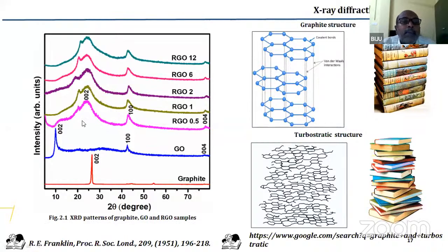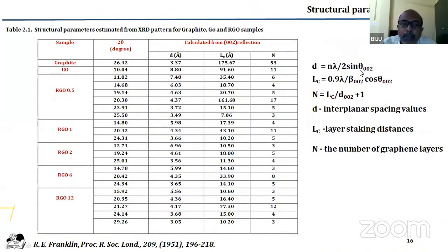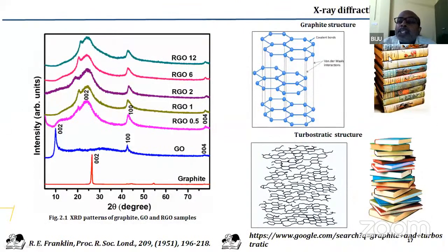Actually this broadening has happened due to the fact that when these layers are restacked, they are stacked in a disordered manner. In fact, this blue diagram shows a typical graphite structure, whereas the bottom one shows what we have obtained, which is called a turbostratic structure. As an analogy, we have shown graphite layers like books which are properly arranged, where the layers are all in the same orientation. Whereas in the bottom figure, you can see the turbostratic structure, where a particular set of d values are here, then a particular set of d values in another orientation, and so on. That is what we have obtained from our XRD.